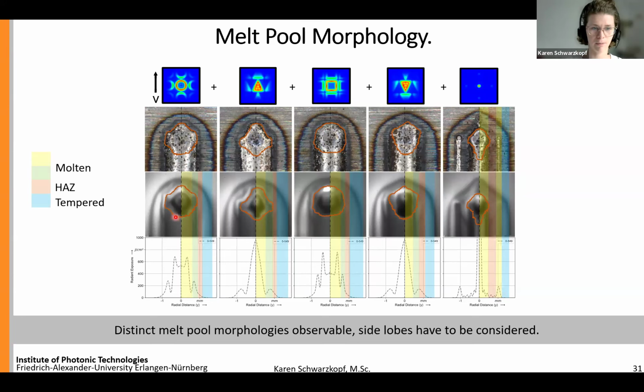And if we are now comparing the morphology of our melt pools, we can see two types, namely the ring and the square beam shapes, which have a straight transition between the melt pool and the solid material, whereas the other three beam shapes rather have a teardrop-like melt pool, where we are expecting different conditions of cooling behavior depending on the center and the sides. So in the center, we're expecting to have a slower cooling compared to the sides.